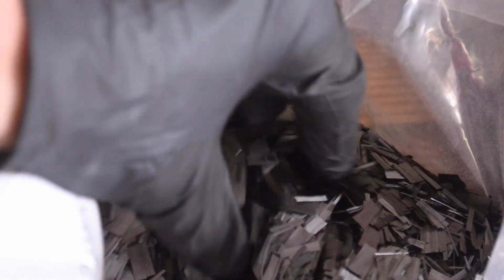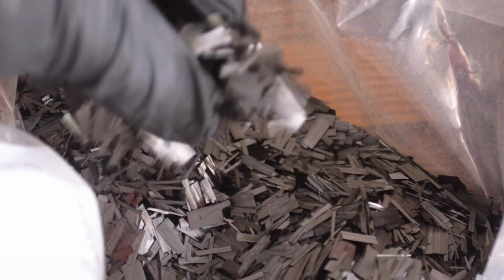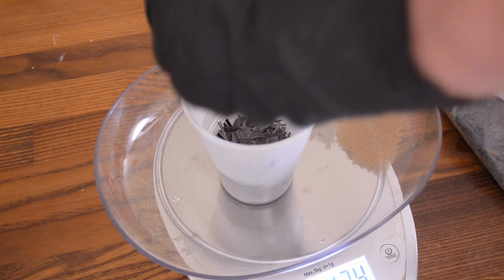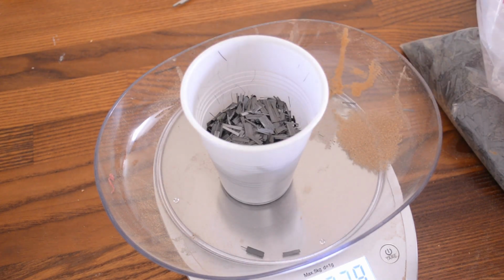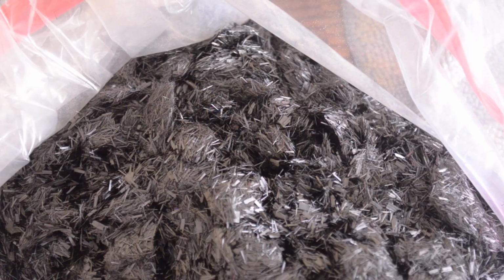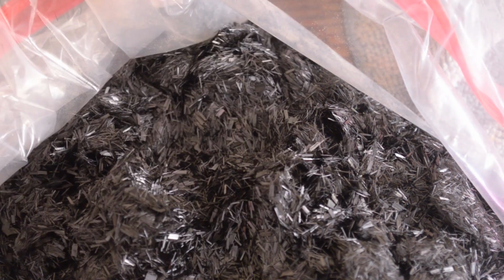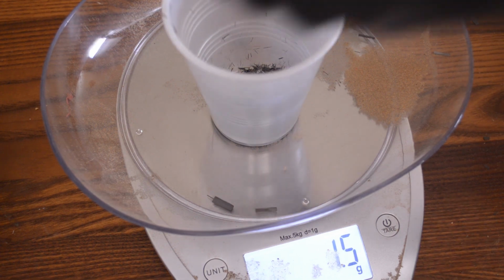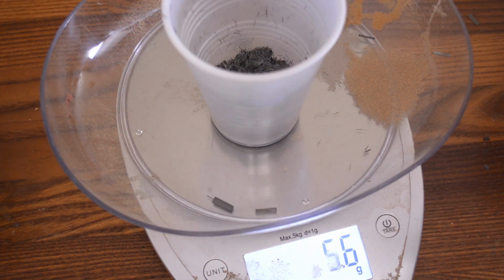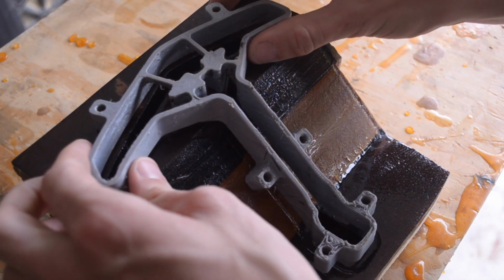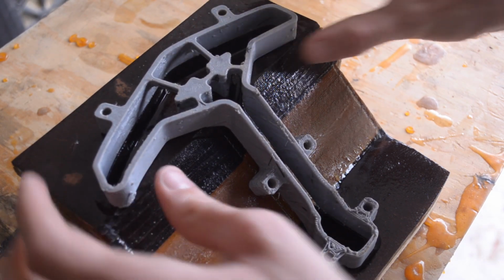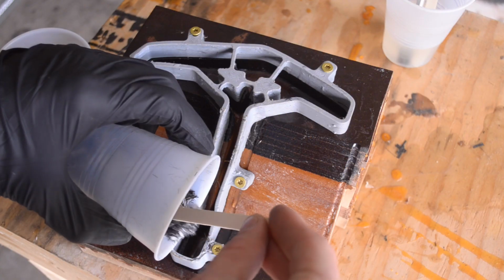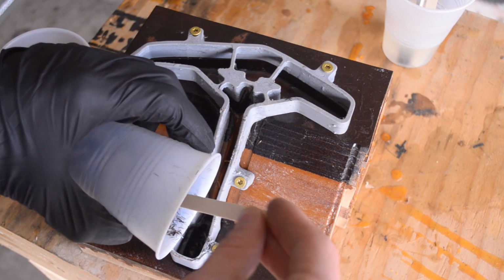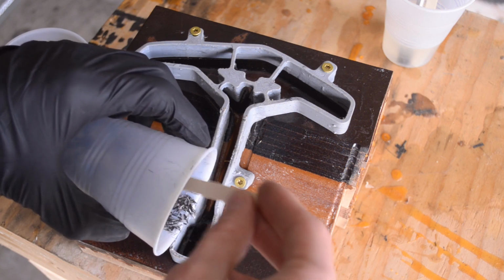And I use both a long strand fiber, about half an inch, and then I use this 1/8 inch stuff for any sort of areas where I had a higher void content in previous revisions. And this gives me a good blend between surface finish, strength, and void content. So I'm pretty happy with the formula I have right now, and it's pretty good. I also made this little plastic layup tool, so all the carbon fiber I put in dry doesn't fall all over the place and make a huge mess.